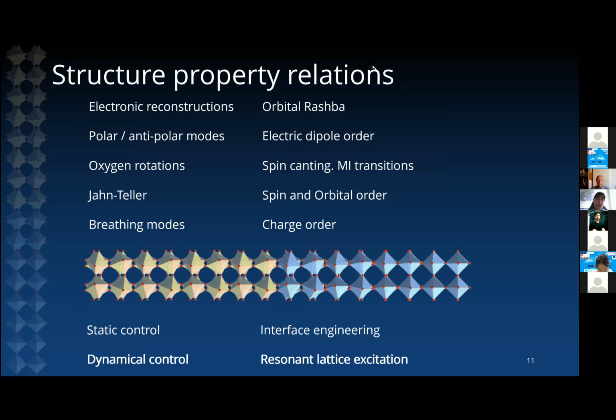And these are all associated with various electronic properties. So to polar and antipolar modes, as I mentioned before, we have associated various types of electric dipolar order. To oxygen octahedral rotations, we can associate spin canting and metal to insulator transitions. To breathing modes, we can associate charge order and so on. So there's a vast space for exploration here. And in our lab, we explore both static control of this type of structure-property relations, so through interface engineering. We interface materials with different crystal symmetries and control their structural distortions at the interface, as well as dynamical control, which is what I will talk about today. So through resonant lattice excitation.